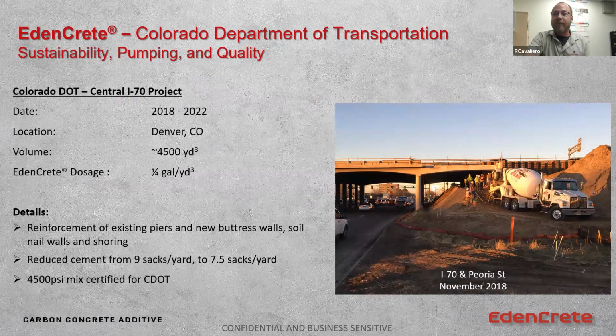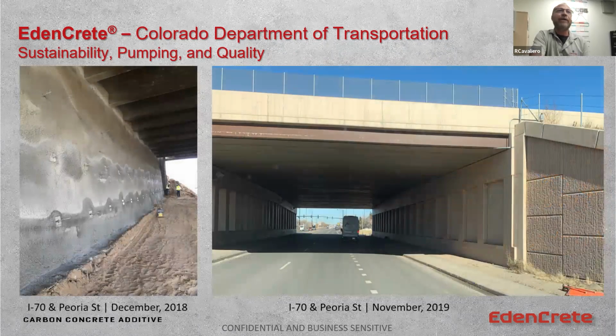When we went out, we were doing things like this, right? 12 miles along I-70, we're expanding bridges, we're expanding underpasses, we're taking 45-degree abutments that you see there that are dirt. We clear them out. We use shotcrete to reinforce the caissons underneath. And then we take precast panel walls and put them up. What this does is we add a lane of traffic, and we actually add a passenger walking sidewalk as well to actually expand capacity under these.